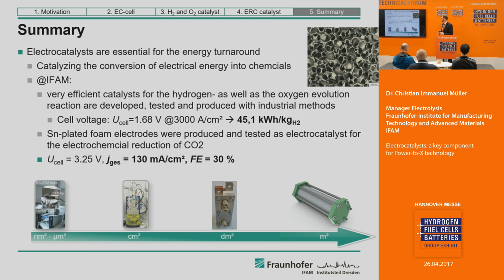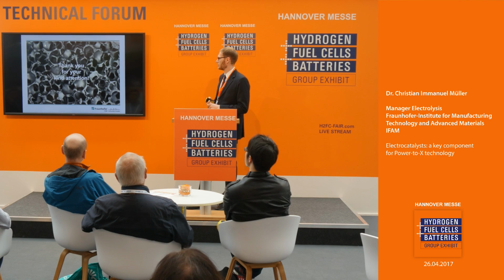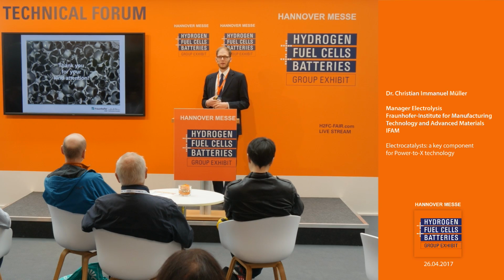And we were able to develop long-term stable electrodes, and the cell voltage was around 1.68 volts, and this means that we need around 45 kilowatt hours to produce 1 kilogram of hydrogen. Also, I've shown you that we can convert carbon dioxide to a valuable chemical, in this case formic acid, with a simple reactor by using just copper foam, which is electroplated with tin. So this was my last slide. I would like to thank you for your kind attention, and thank you.